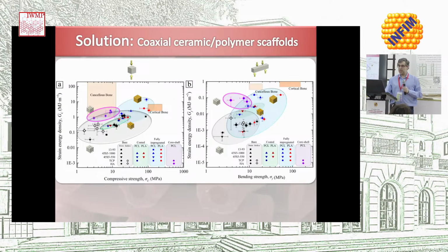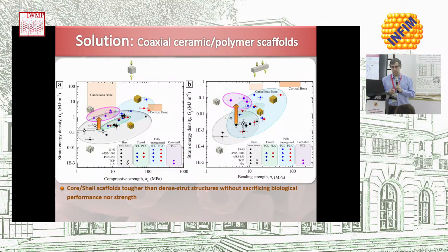And as you can see here, those are some of the results that Antonio already mentioned, and the materials that I'm highlighting there are the new ones with the coaxial structures. And as you can see, we have improved the toughness. We have materials that are tougher than dense structures, but without sacrificing biological performance, nor strength. Strength is still more or less the same as the dense structures, which is pretty good. And we are improving toughness even over coatings. Okay, coated materials do not produce as tough structures as we can produce with this coaxial strategy.